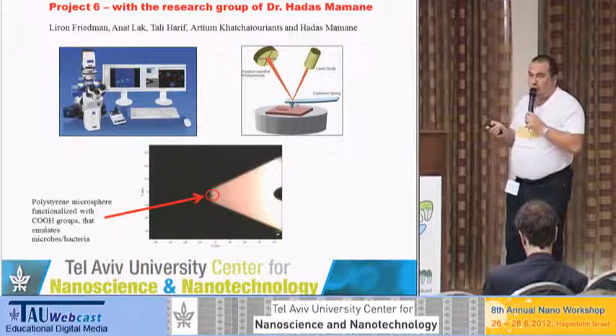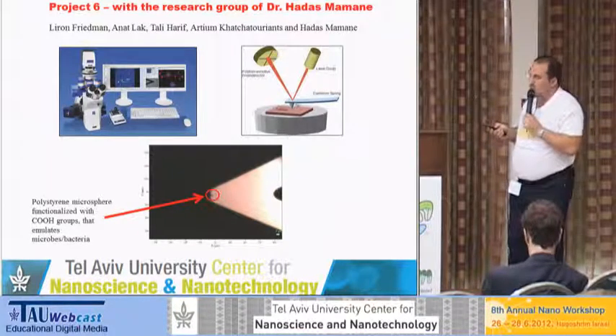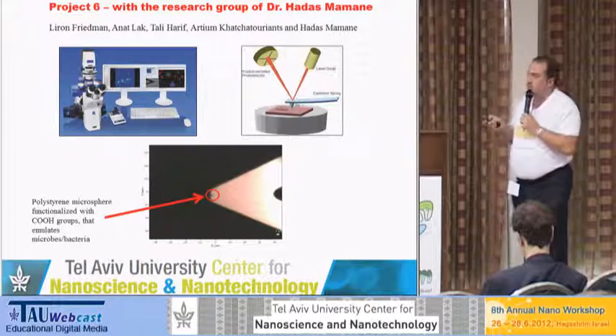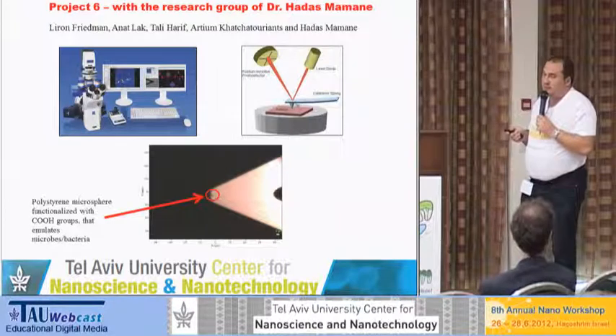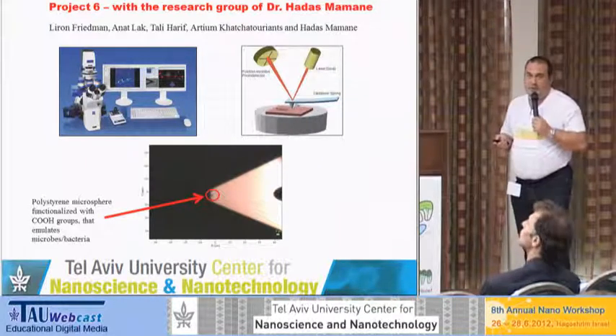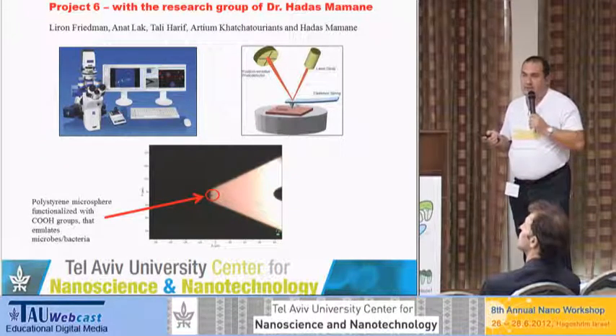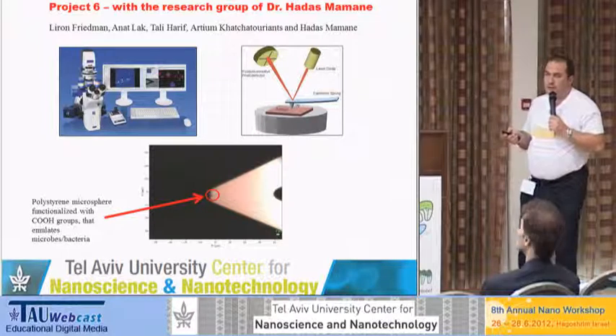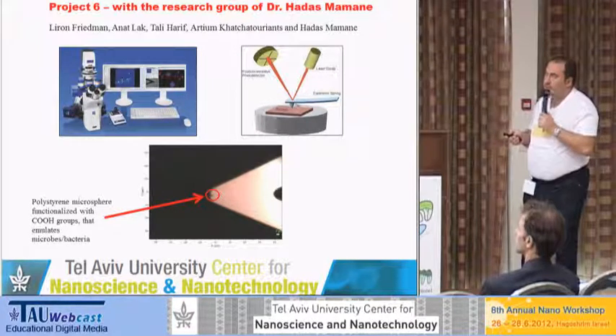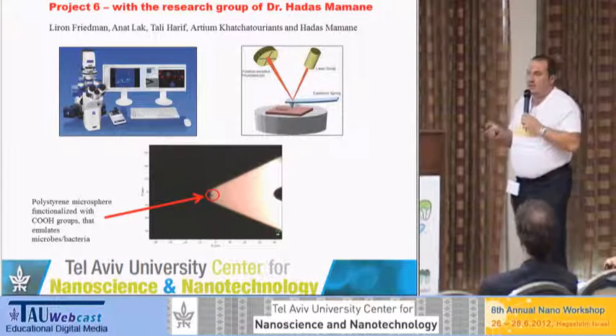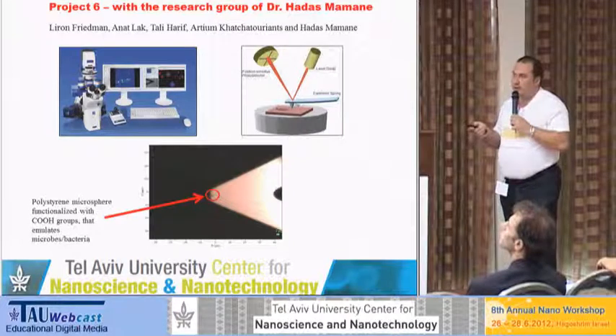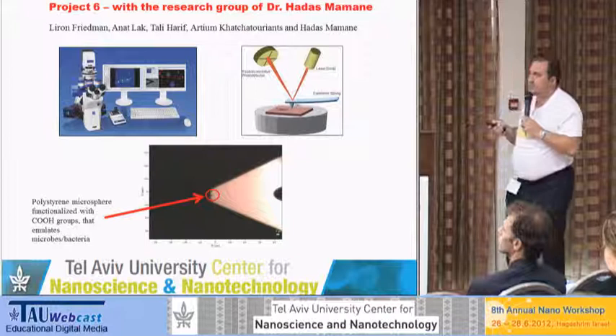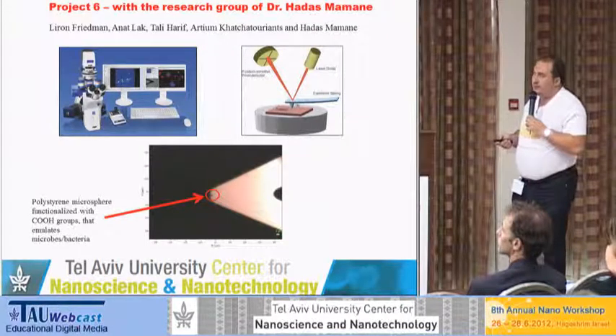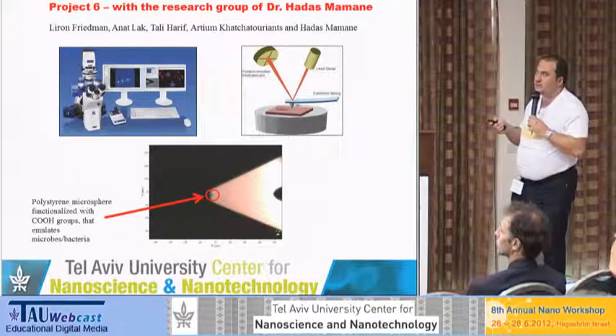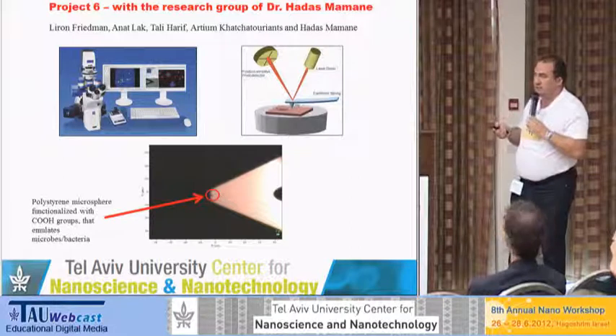Very similar research, actually also very interesting. Unfortunately, we obtained too variable results, but still I would like to present it because it's a quite promising technique. And this is about biofouling. As you know, in water pipelines there are contaminations because of adhesion of microbes and bacteria to the pipelines. And the aim here is to investigate materials and probably treatments to these surfaces, from which pipelines can be made, with the purpose to eliminate or significantly decrease this adhesion.